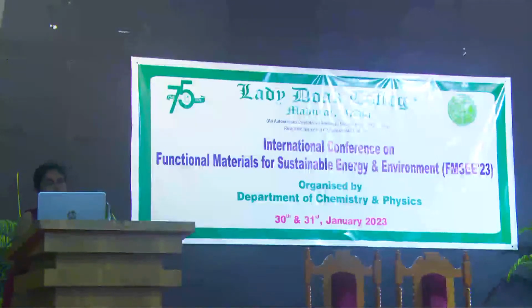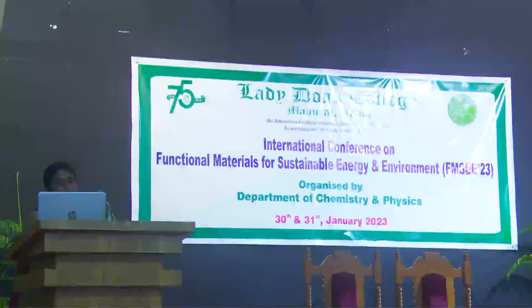So conclusion. The study concluded that biodegradation of chromium is possible in FMSEs within the limits of 0.1 normality to 0.2 normality. My best work is 0.2 normality chromium 6 loaded. FMSE clearly revealed the chromium toxicity.